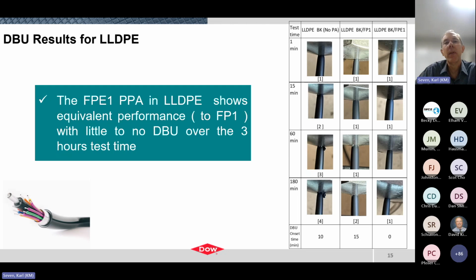The onset of the buildup is quite rapid, actually. The middle series of pictures is the series with the typical fluoropolymer additive, and as expected, there's very little buildup throughout the period that we're testing. Finally, the last series of pictures is with the polar polymer additive at the same concentration as what we used in the medium density studies, and it works, as can be seen here. It's very effective and actually slightly improved.